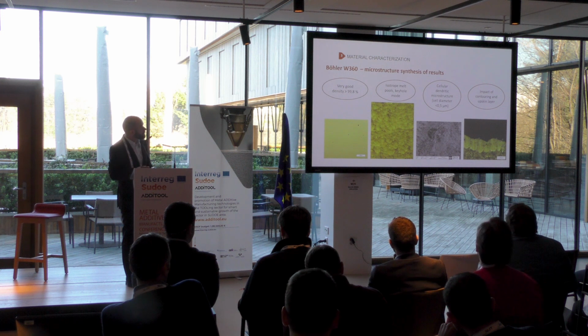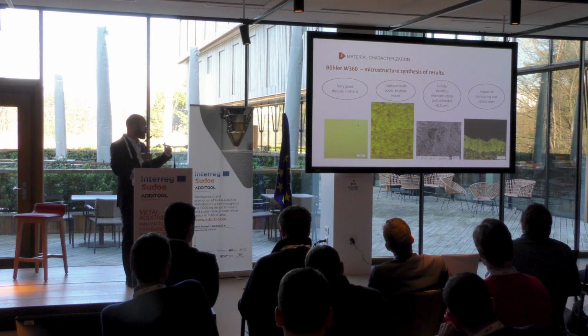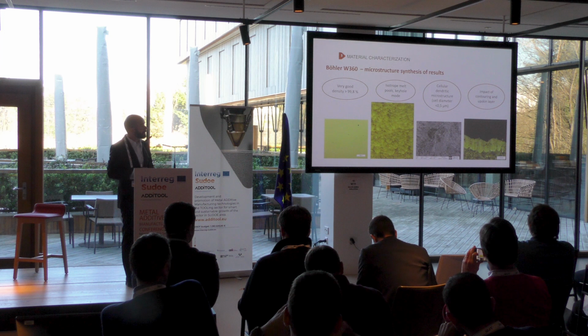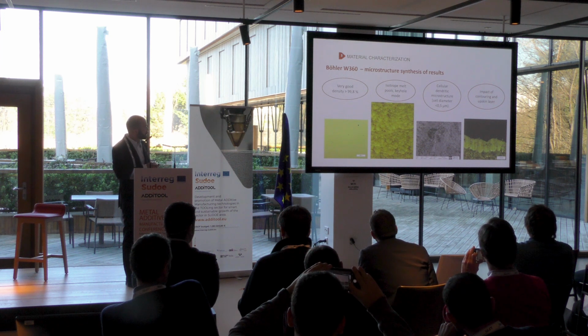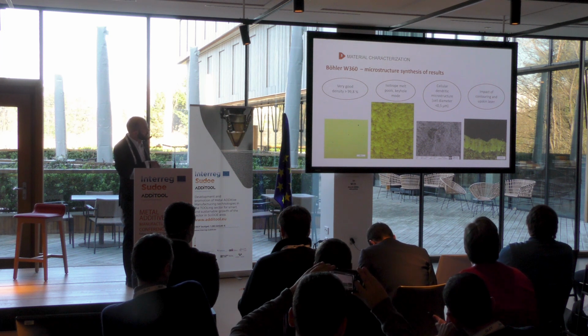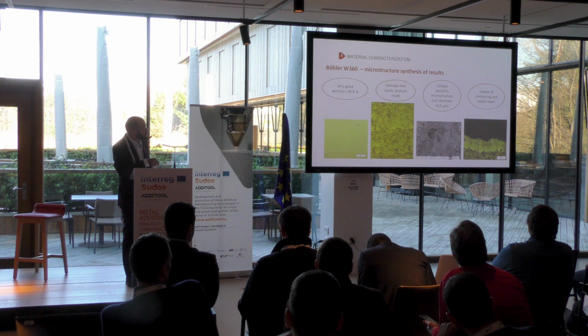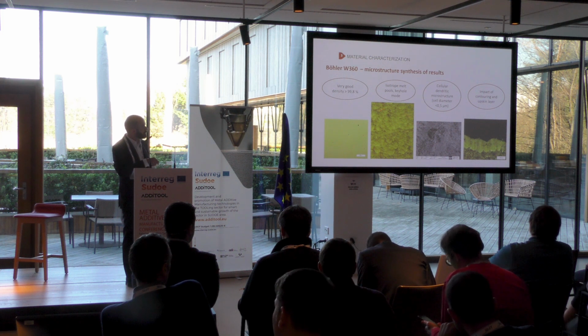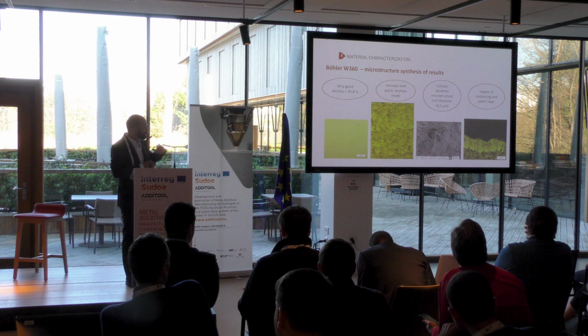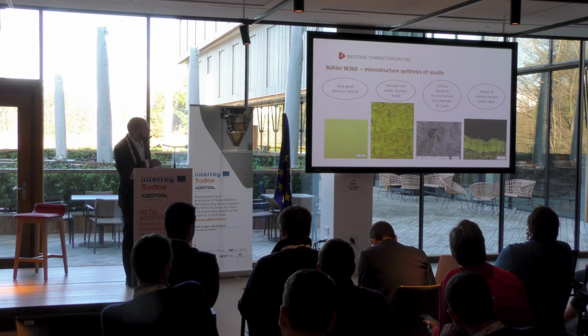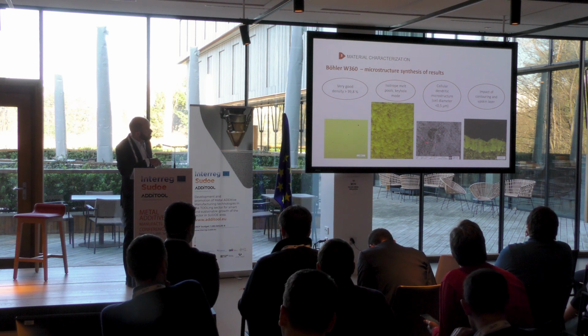The microstructure and specimen characterization were performed by ENIT. We can see a very good density, and a typical microstructure from the SLM process without any sort of heat treatment. We can see that here as well.